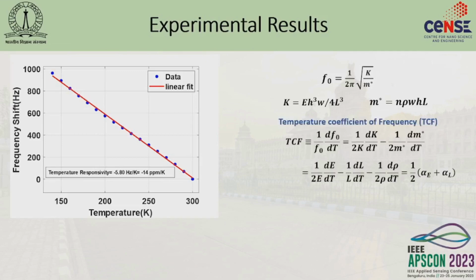Based on this, we calculate the temperature coefficient of frequency, which depends upon the change in stiffness term and the change in mass term. If we write it in terms of Young's modulus, the geometrical term and the density term, the final value depends upon the temperature coefficient of Young's modulus and the temperature coefficient of linear expansion. Since I have used silicon nitride as the structural material, the temperature coefficient of linear expansion is about 3 ppm per Kelvin, and the temperature coefficient of Young's modulus is about 48 ppm per Kelvin. Based on this, the theoretical temperature coefficient of frequency is about minus 25 ppm per Kelvin. But experimentally we are getting about minus 14 ppm per Kelvin.